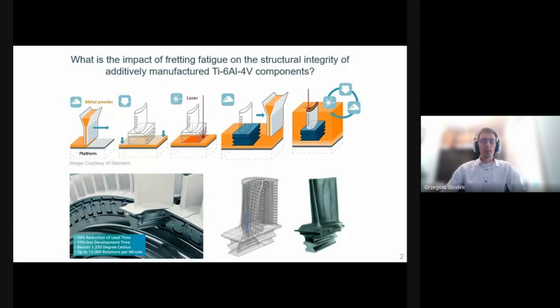The additive manufacturing process in question is selective laser melting, in which metal powder is first deposited on a build platform, and then a single slice of the part is created by a laser. Afterwards, the build plate moves down by a layer, and the coater spreads a new layer of the powder on the build plate, which is subsequently melted by the laser again. Now this process repeats until the entire part is finished.